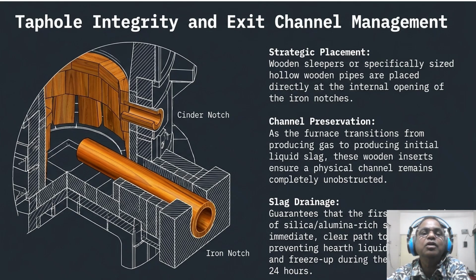This first accumulation of slag is often silica and alumina rich, making it incredibly viscous. So here is the slag drainage. Now if you don't have a clear path to exit, the liquid will accumulate and freeze, causing a hard freeze-up within the first 24 hours. So we are essentially pre-drilling our exit route with organic material that will burn away exactly when we need the liquid to flow. Now that we understand this logic, let's look at the specific layer arrangement used